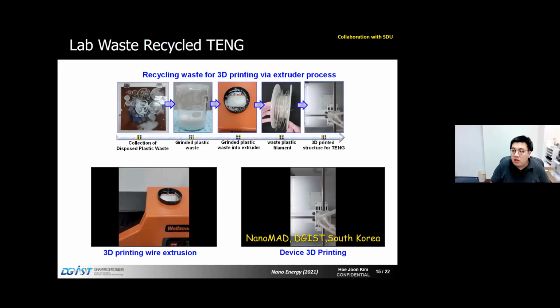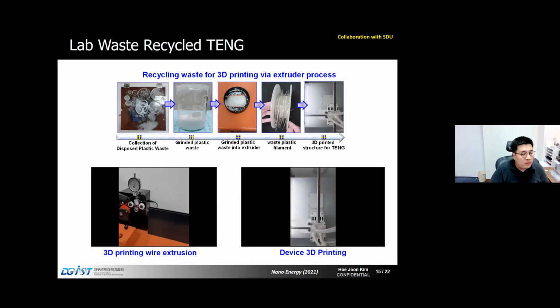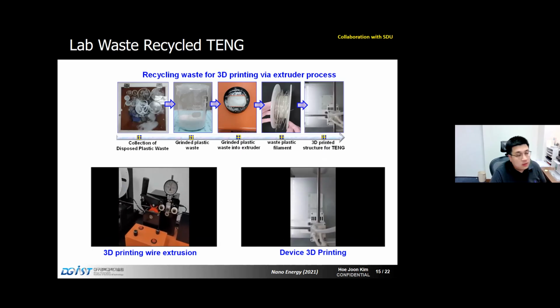So what we did was that using the plastic, we can actually melt this plastic and extrude it into a wire shape, and we can put it into the 3D printer. We can just use the polymer source and print a structure. So we are able to make the device using this 3D printed recycled plastic. Many people are trying to recycle polymers, even ceramic powders, and using them for additive manufacturing.